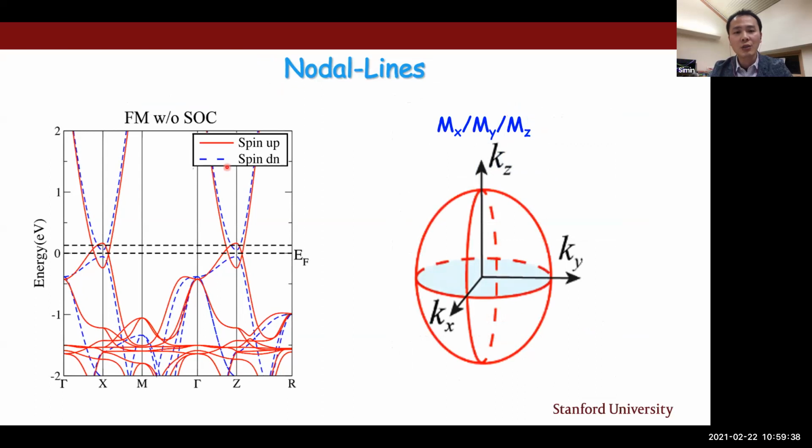Okay, another interesting result in this band structure is the existence of the band inversion at the X point for the spin-up states. Due to the protection of the mirror symmetries, we can find 5 intersecting nodal lines around the X point. 3 of them are shown here.